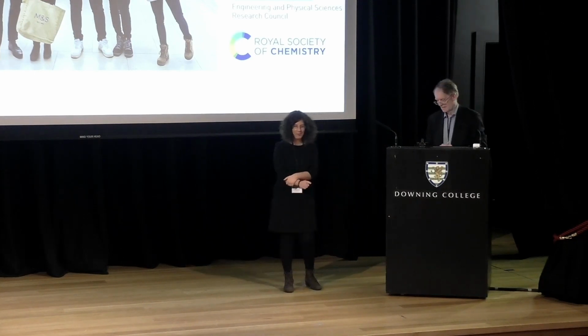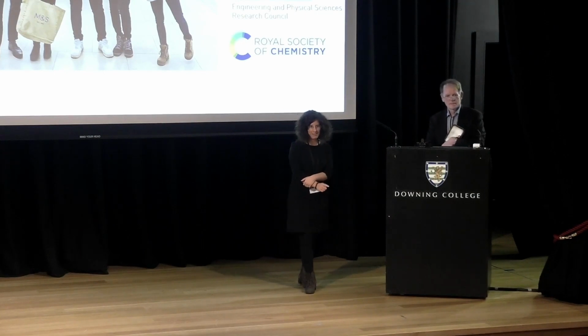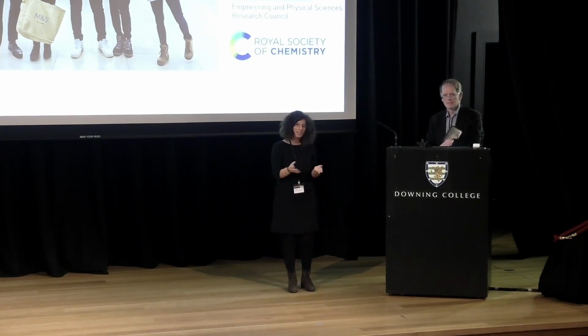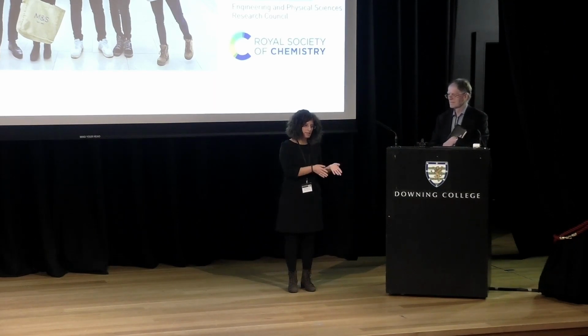Right, yeah. So it's a great question because it took me like 3 months to get nice pictures of those nanoparticles back in time. And the reason is that, you're right, there's a different contrast, because the ethanol sample you can image a lot better than the water samples. Water samples are a lot harder to image by TEM. So the actual staining is the same. It's uranyl acetate that we use. But actually, those pictures, I think, if I remember correctly, were taken using a graphene oxide grid. So graphene oxide is the material that works best with nanoparticles in water, compared to normal TEM grids that you would use for nanoparticles in ethanol, and you would just add the staining there. So that's the different contrast that you see, yeah.